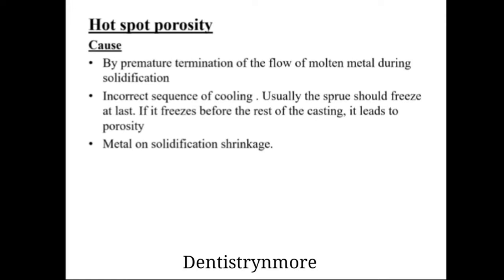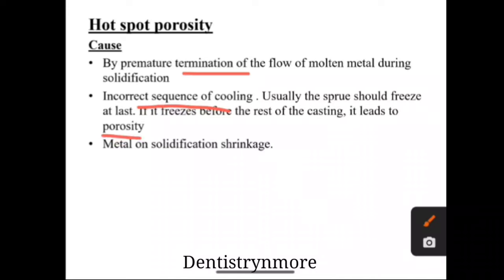Next one is hotspot porosity, and it is caused due to the premature termination of flow of molten metal during the solidification, and there is incorrect sequence of cooling. Usually the sprue should freeze last, and if the sprue freezes before the rest of the casting, it may lead to porosity.